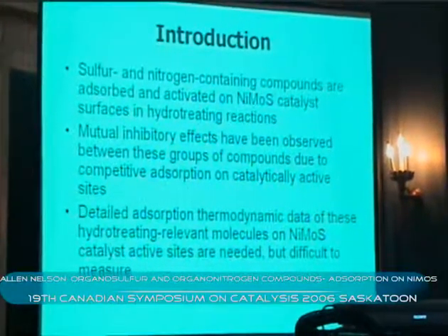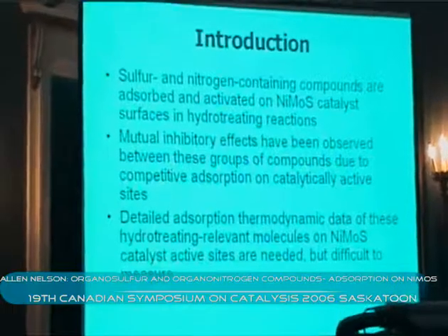Our motivation for this study was to begin to understand the salient features of those mutual inhibitory effects between organosulfur and organonitrogen compounds on the well-defined nickel molybdenum sulfide edge surface. The only thing that I would add to some of the previous discussions is that it's previously been reported that one of the key limiting factors, if not the key limiting factor, preventing the complete desulfurization of 4,6-DMDBT is the presence of basic nitrogen species in the feedstock.